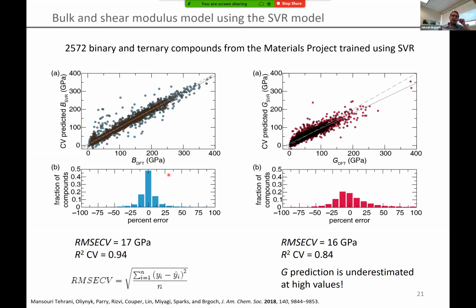Now the shear modulus is not quite as good. You can see that the shear modulus R squared is only about 0.84. Root mean squared error, though, is about 16 gigapascals. This is still reasonably good, but if you look at the parity plot you can see it's not ideal — there's significantly more scatter. The shear modulus data tend to be clustered a lot lower, between 0 and about 200. You get some really high shear moduli up here, but above 200 gigapascals you're starting to talk about really sparse data, and that's probably why we get significant underestimation at really high shear modulus values. You can see that reflected in the histogram here — not really that reliable of a prediction overall.